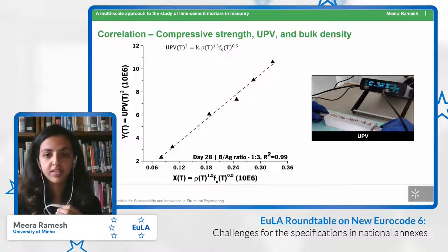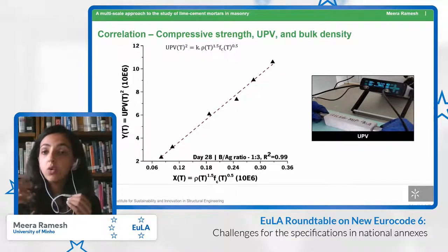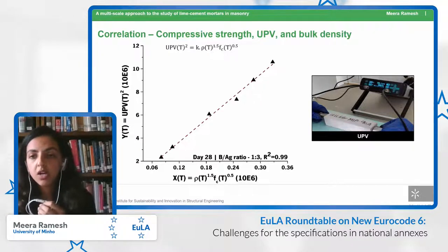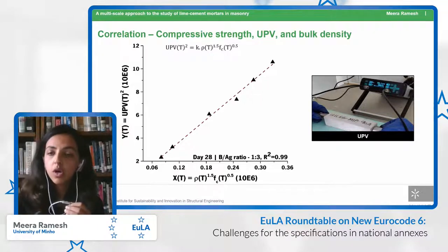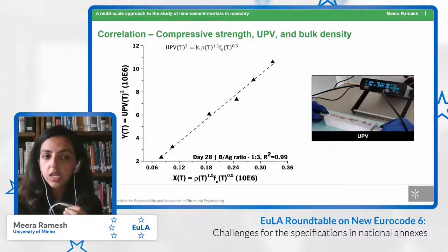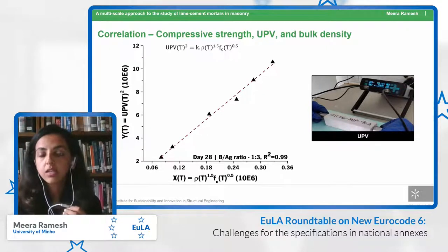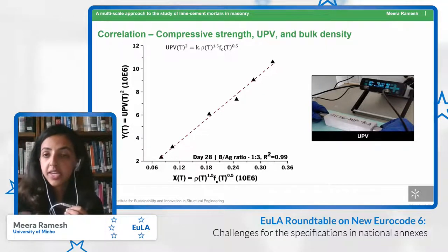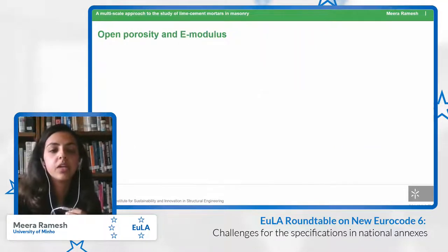Which means that at any age, if you can weigh the mortar specimen, and you know the volume, so therefore you find out the hardened bulk density, and if you are able to measure the ultrasound velocity, you should be able to estimate the compressive strength. Again, this is valid only for the set of materials that we have tested so far.